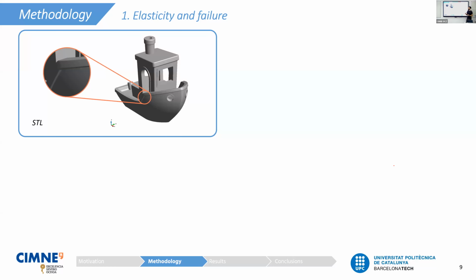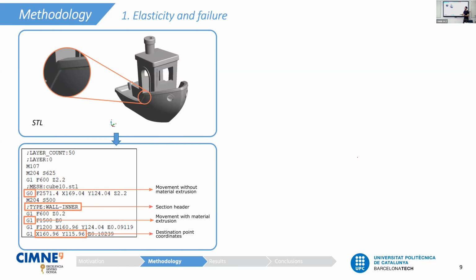However, this STL is required because in a fused filament fabrication process, this STL file is sliced at several heights, and the intersection between a horizontal plane and this STL file forms a path, and this path is the one that is used in order to fabricate the component. The translation from this STL to this code, called G code, is called a slicing process. And since this G code still contains all the geometrical information that we require for the component, it is the one that we are going to use to generate our mesh.